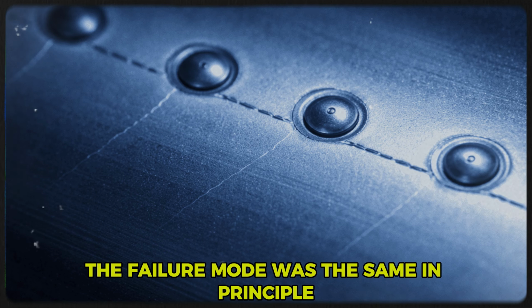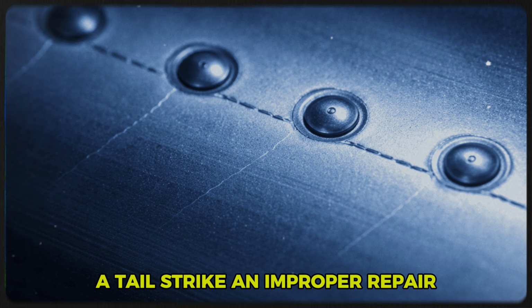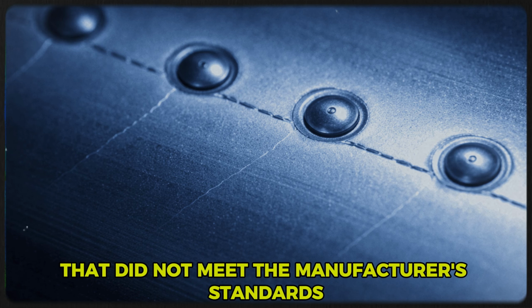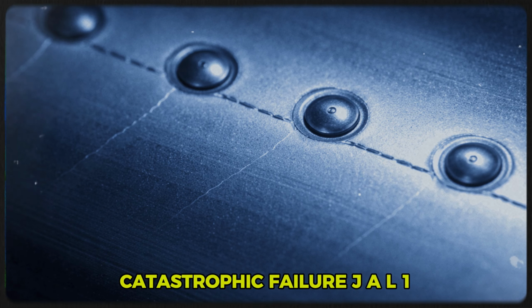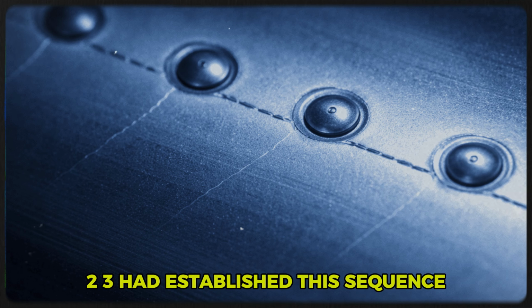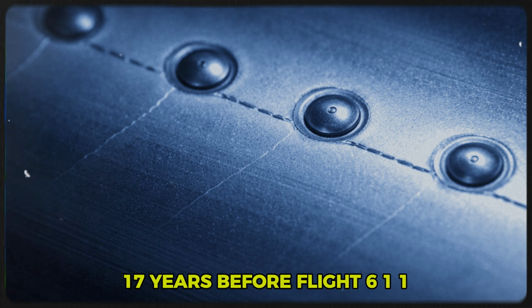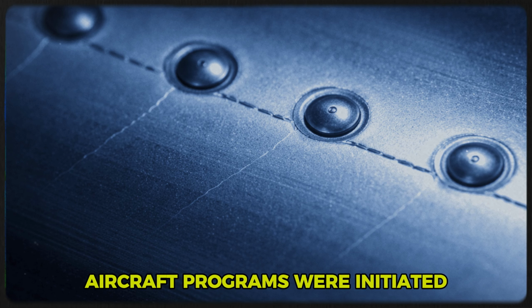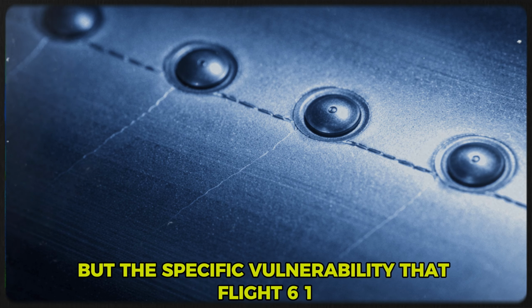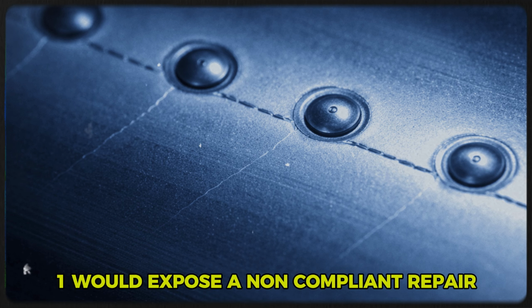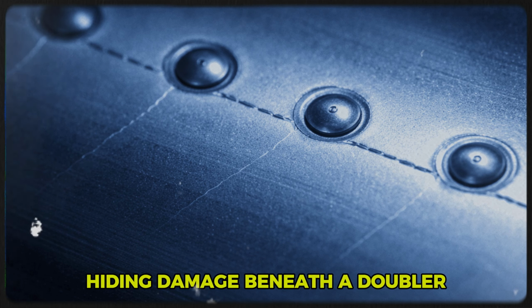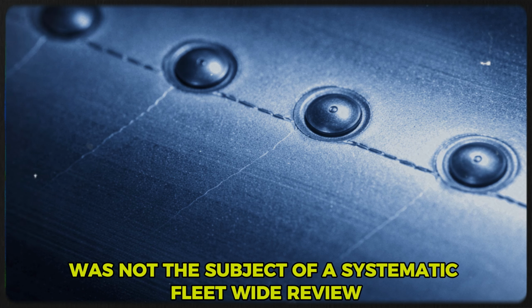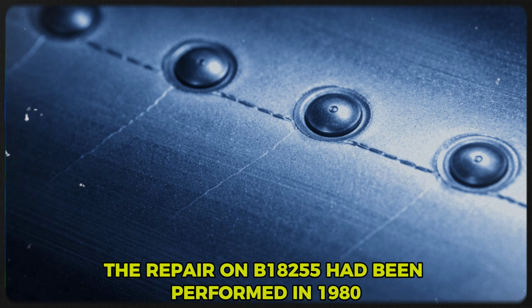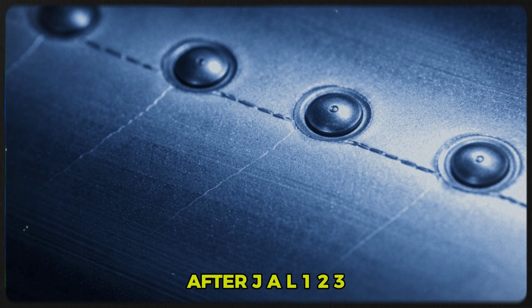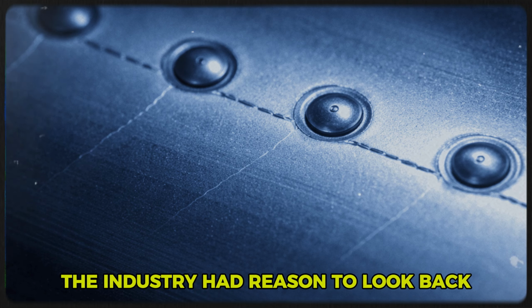The failure mode was the same in principle: a tail strike, an improper repair, a doubler that did not meet the manufacturer's standards. Progressive structural degradation, catastrophic failure. JAL 123 had established this sequence 17 years before Flight 611. The industry knew. Aging aircraft programs were initiated. Inspections were mandated, but the specific vulnerability that Flight 611 would expose, a non-compliant repair hiding damage beneath a doubler on an individual aircraft, was not the subject of a systematic fleet-wide review. The repair on B-18255 had been performed in 1980 before JAL-123 occurred. After JAL-123, the industry had reason to look back. It did not look at